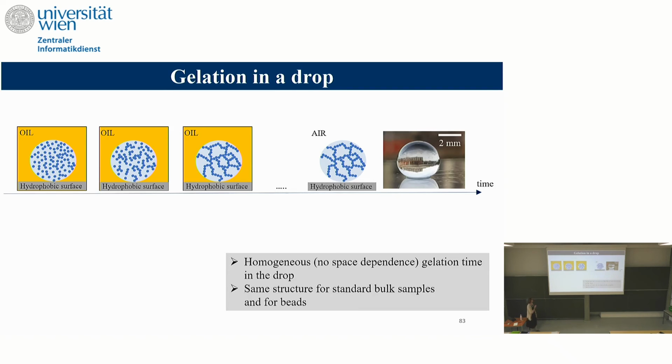You put a drop with colloids, and then we add an enzymatic reaction to produce salt, and then to induce aggregation of the particles into gel. And then we have our gel, we take this bead, they are typically a few millimeters, like the drop actually, a few millimeters of diameter, and we look at what's going on when they dry.